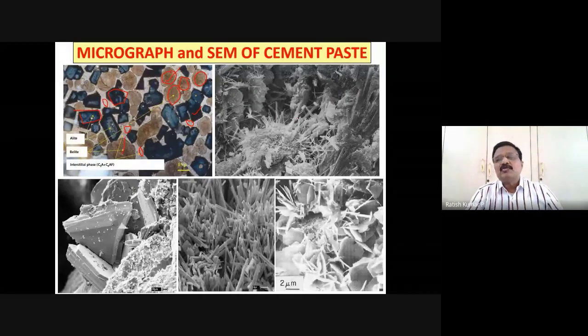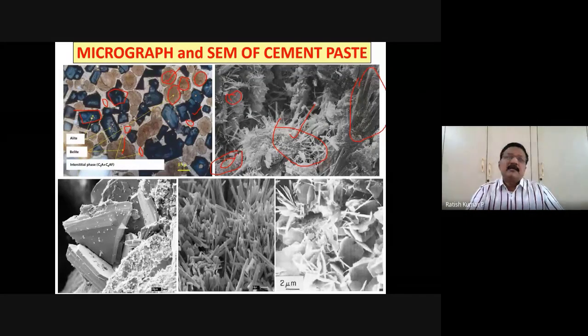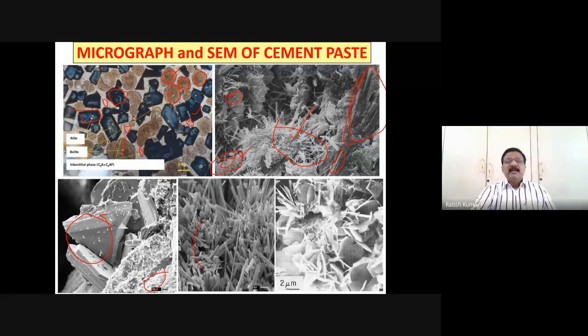And if you see the scanning electron microscope image, with some magnification, something like 2 micron, or this one is around 10 micron or so, you can see certain precipitates, certain needle-like crystals, and certain rod-type things. Now these are ettringites. These are gel-like elements, something like CSH gel, which can be totally hydrated or slightly unhydrated, or there can be portlandite phases, which are identified by these rod-like phases. The same thing you can notice here. For example, the CH, the gel, which is CSH, and the needle, which is ettringite, and these are certain CH as well as this is CSH. So that's what you can notice here.